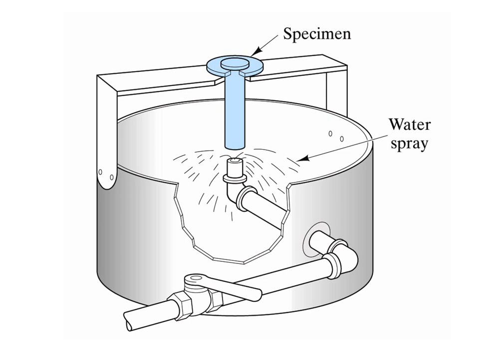So the Jominy itself is a standardized test for one inch bar. This is the specimen, exact shape, size, diameter, length, and this has been cooled in a very specific environment. The apparatus looks like this, so this comes with a half an inch water jet with a certain temperature, the pressure and so on.